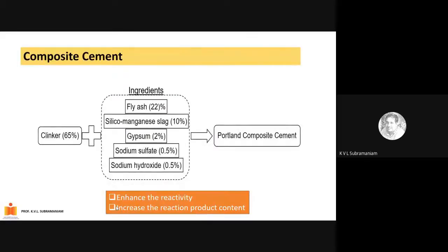The next step was actually to produce the composite cement, which was to take the clinker and combine it or blend it with other materials. And the whole objective is to enhance the reactivity of the system, and to increase the reaction product content in the system. I want to produce more calcium silicate hydrate in the system. For that, I have to bring in additional sources of silica into the system. So we know that I can use fly ash. Fly ash has reactive silica. It can be used as a supplementary cementitious material. Slag also contains reactive silica. It's also used as a supplementary cementitious material.